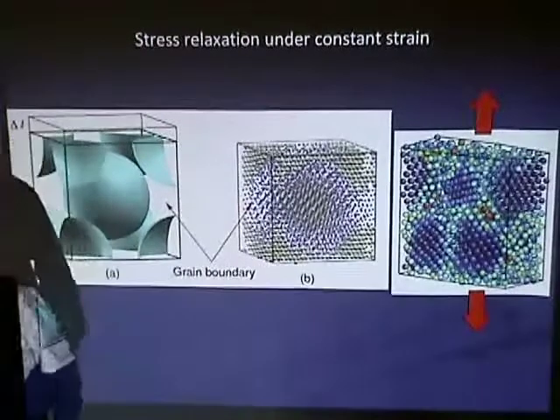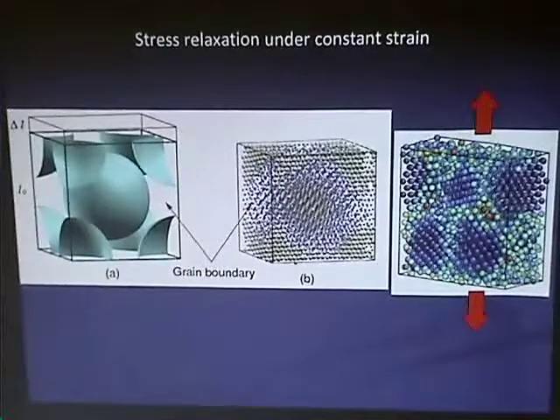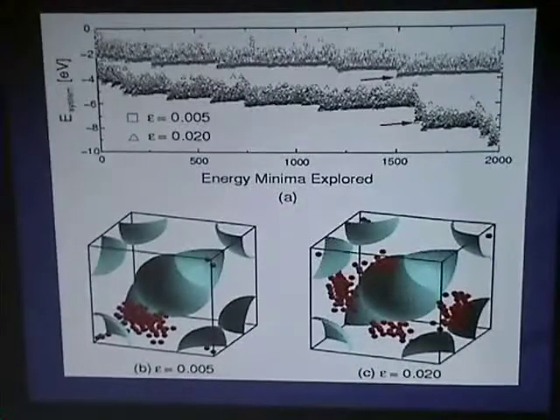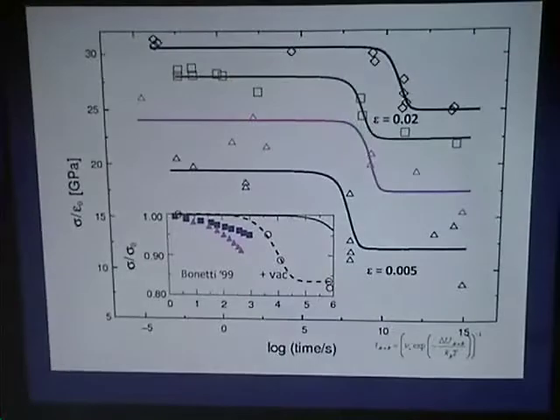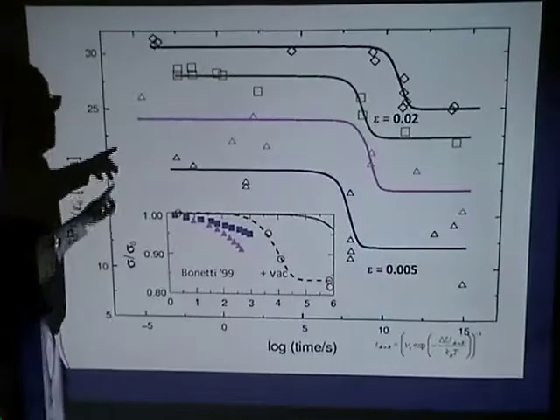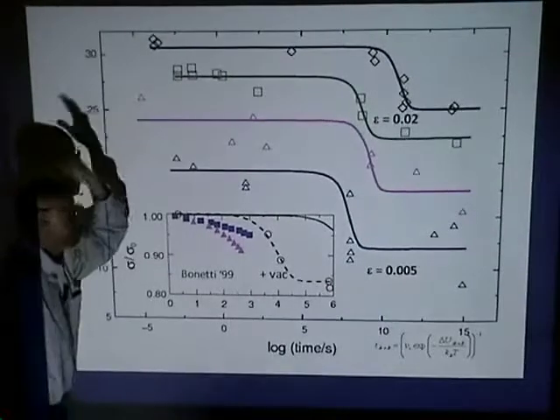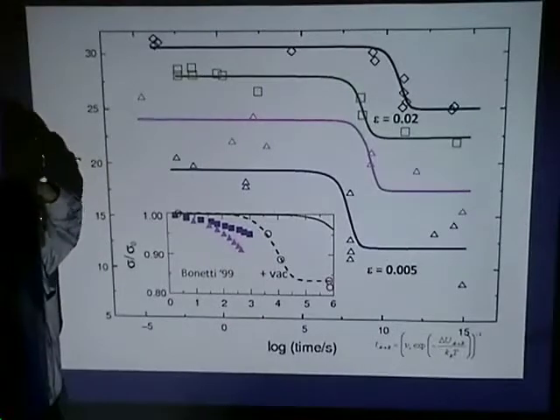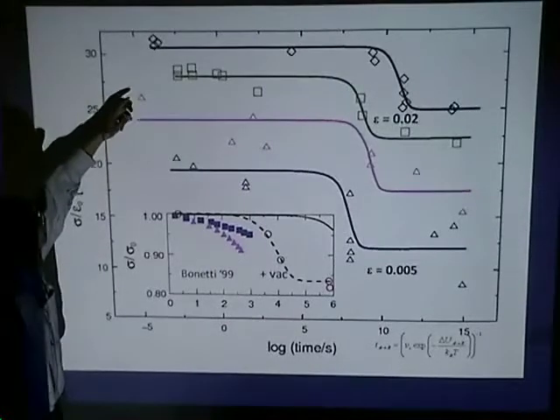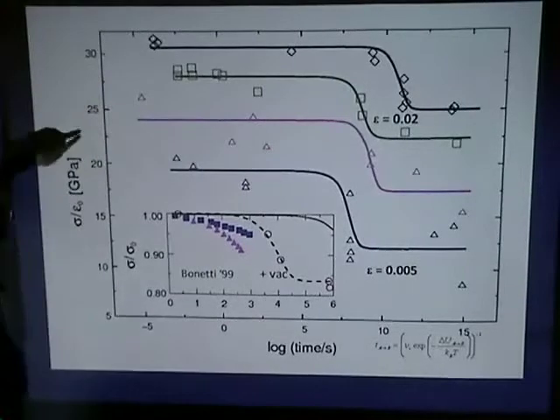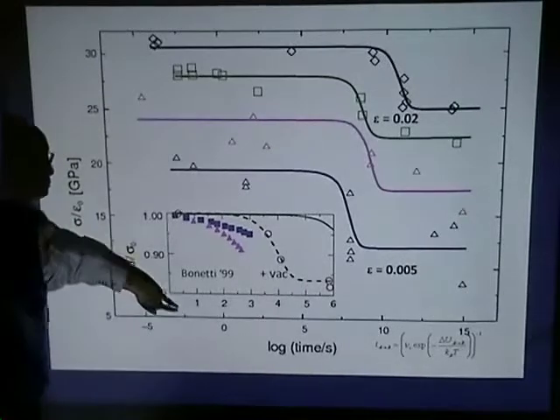So this ideal simulation shows something like this, and this is the mechanism I can come back to. Basically you have this classic relaxation behavior of inelastic relaxation. We're plotting the stress in the system as a function of real time in units of seconds, on a log time scale.